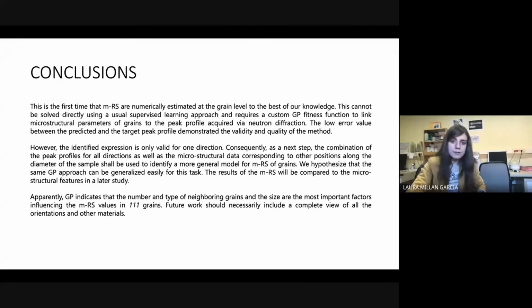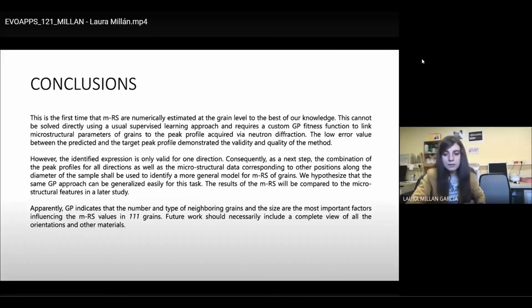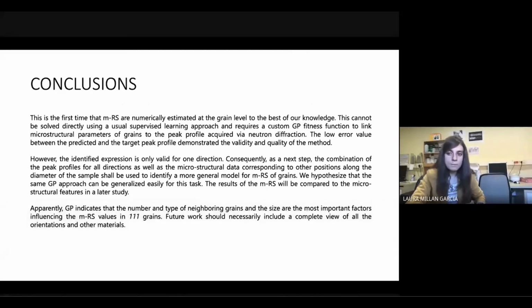However, the identified expression is only valid for one direction. Consequently, as a next step, the combination of the peak profile for all orientations as well as the microstructural data corresponding to the other positions along the diameter of the sample should be used to identify a more general model for micro-residual stress of the grains. We hypothesize that the same GP approach can be generalized easily for this task. The result of the micro-residual stress will be compared to the microstructural features in a later study.